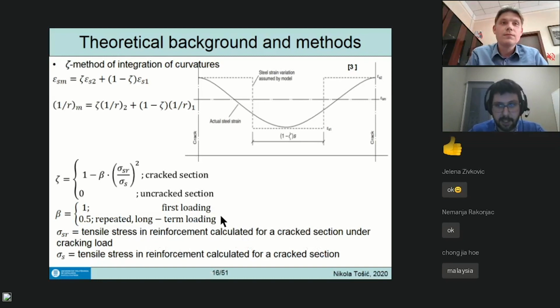So basically at the cracking load, you have a response, infinitesimally before, which is with the uncracked stiffness, or you have it afterwards. That's the jumping curvature that you usually see on moment curvature relationships. So this you calculate with the cracked section stiffness and precisely under the cracking load, and this is going to be your tensile stress for your load. But we'll see also later, it's going to be for the maximum load that you can have in a structure.